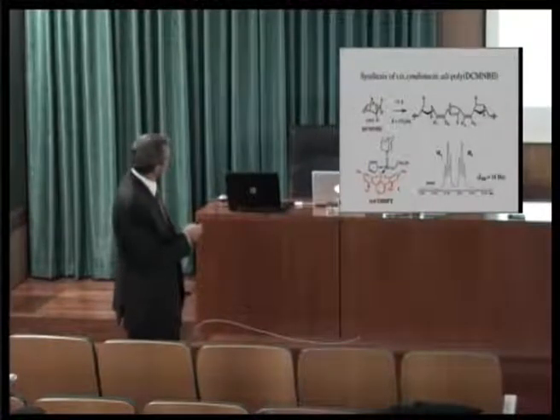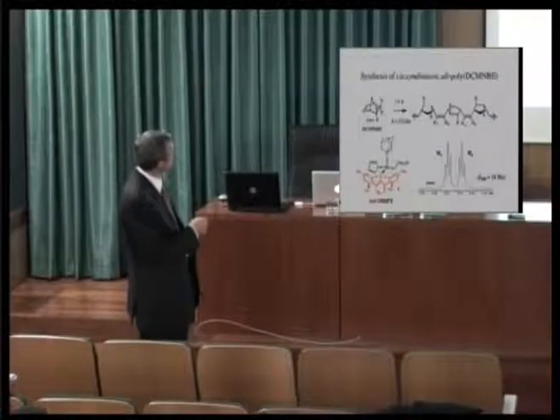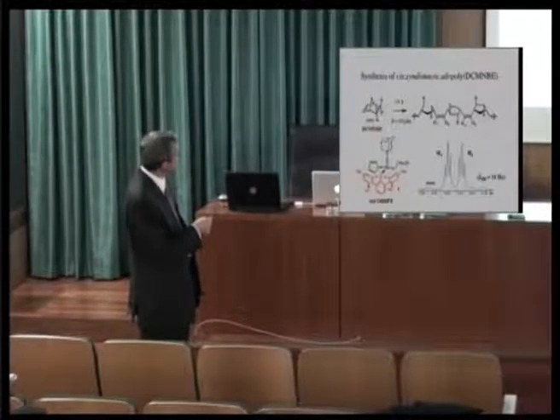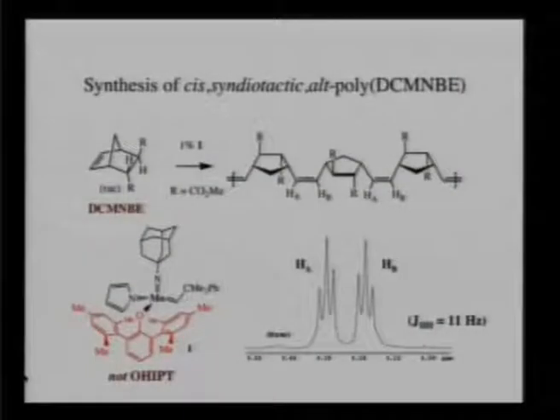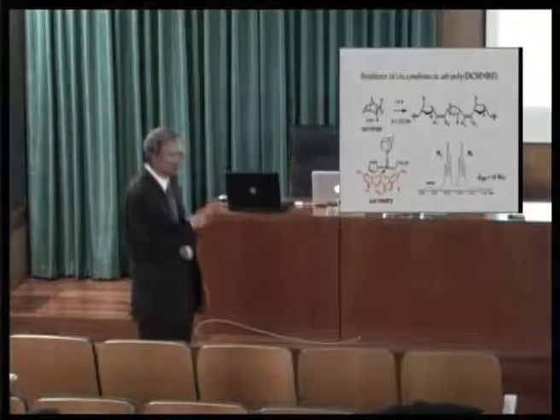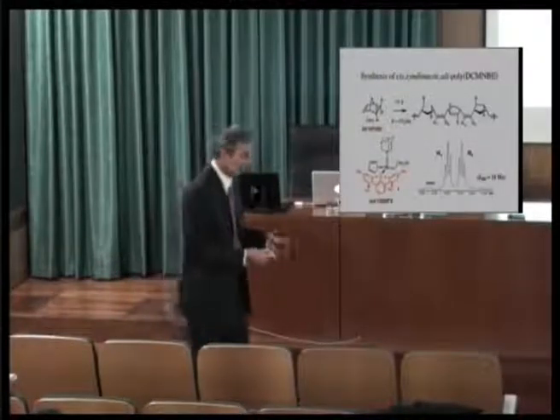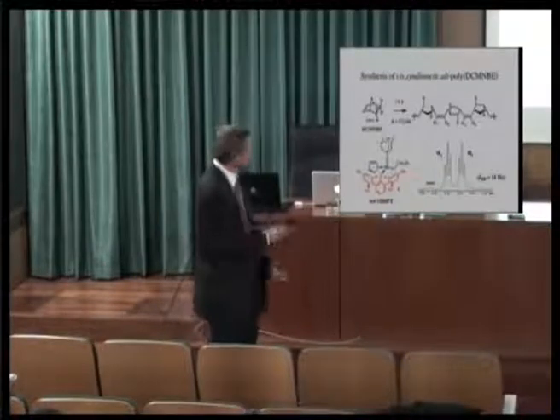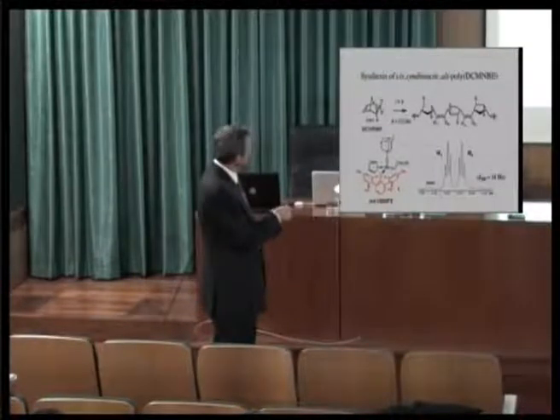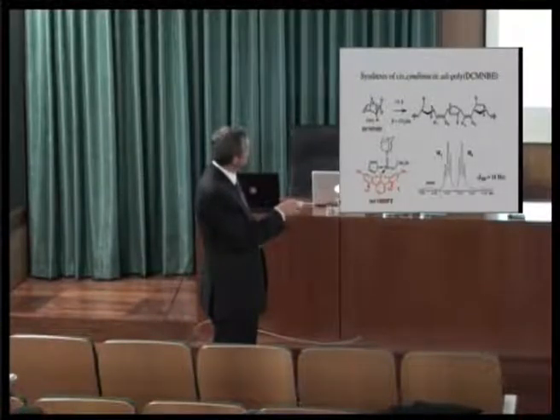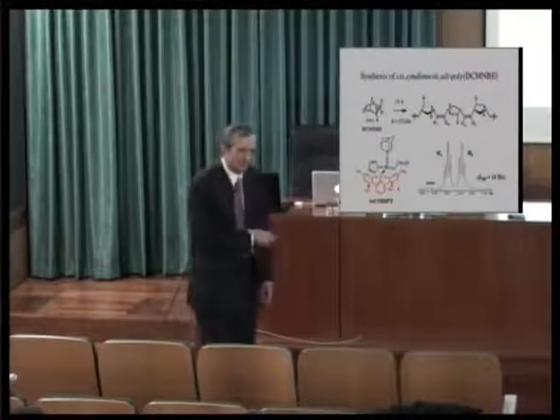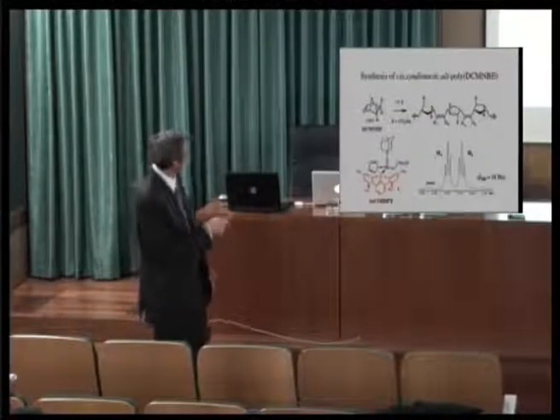So this monomer, for example, is very easily made in a Diels-Alder reaction. These are dicarbomethoxy substituted versions. This catalyst is number one, which is not a HIPT catalyst. It's a hexamethyl version. The hexaisopropyl one does not work well. It's too crowded for this monomer, but this one works well. And you generate then this polymer that has alternating enantiomers in the chain, and you can readily show that by NMR studies that that's the case.